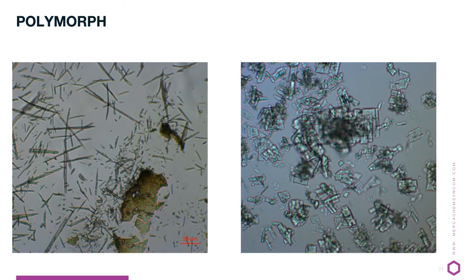Here a clear example of different polymorphs. Needles to the left, block-shaped crystals to the right. The needles will likely have a good dissolution rate, but horrible drying properties, while the block-shaped crystals will have good filtration and improved flowability, but yet might be less soluble.